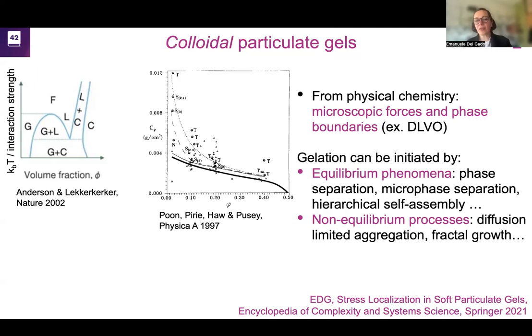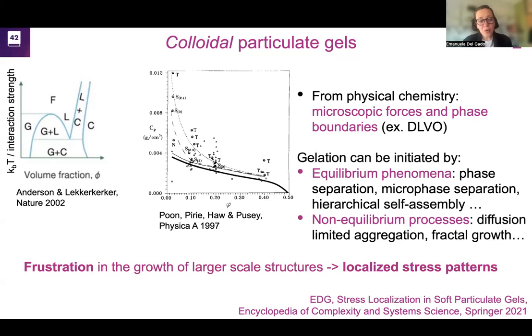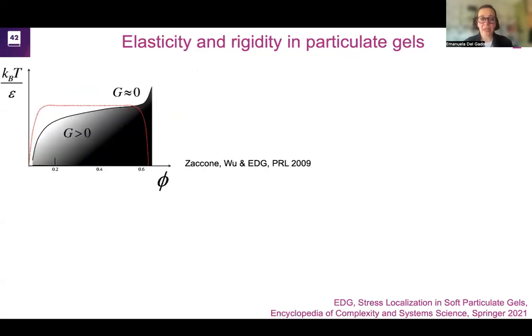In other cases, I will have completely non-equilibrium processes like fractal aggregation, diffusion limited aggregation, where the particles stick together and the interactions are so strong that they just remain stuck. They do not have the possibility to explore their equilibrium states. In all these cases, however, the structure of the gel in the end is the result of this initial aggregation, which has started in different ways, but then aggregation and growth get frustrated into the structure of the gel, where stresses accumulate, as I was describing before with my little distorted network of springs. So I can see in this type of phenomena how stress localization and frozen stresses can emerge.